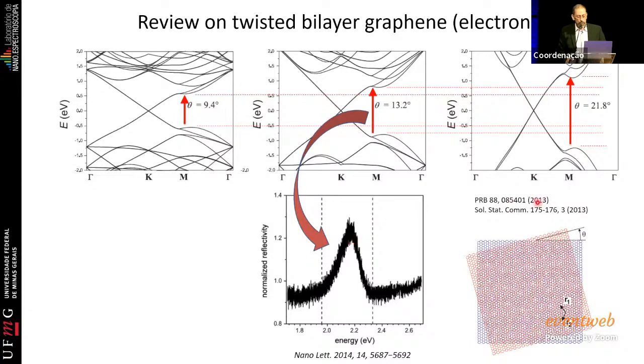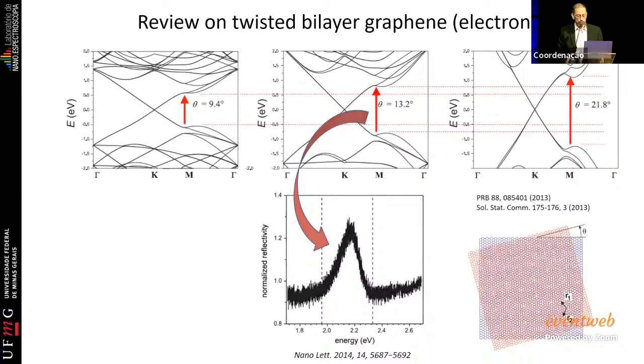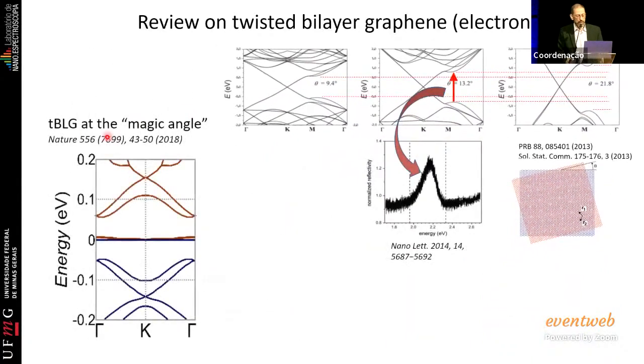And if you go now, here I was showing you a rotation angle of 21.8, 13, 9. And now if you go to very small angles, like the so-called magic angle, the magic angle is around 1 degree of rotation. You also have this high density of states happening at a small energy. Notice the energy here is very minor. Here it was on the order of 1 electron volt. Here it is on the order of 0.1 electron volt.